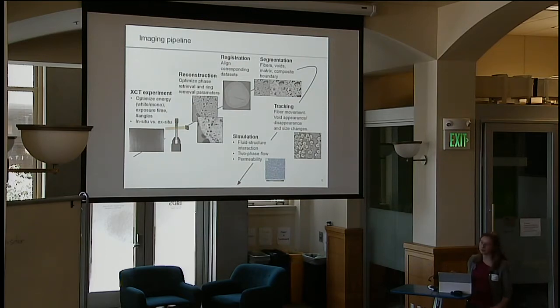Additionally, depending on what type of experiment we're doing, we'll need to optimize these parameters a bit differently. For ex-situ experiments, where the specimen is not changing in time and we're just trying to capture a nice image, we can do relatively slow imaging and capture really high-quality images. In-situ imaging, on the other hand, is when we're imaging it as, for example, fluid is flowing through the fiber bed. Here we need to image quickly enough that we can capture the behavior, but not so quickly that our images are not segmentable and we can't see what's going on.